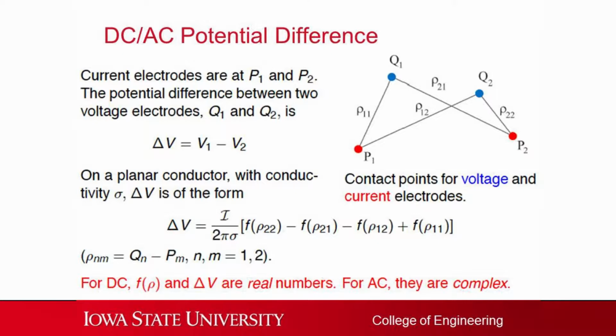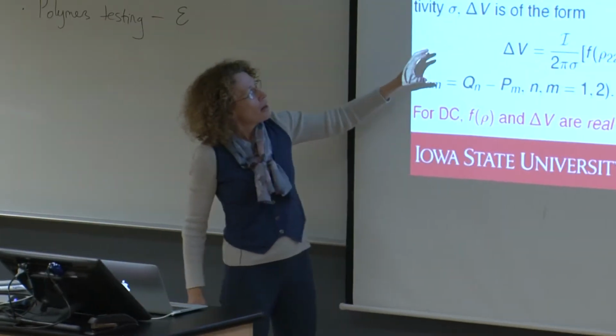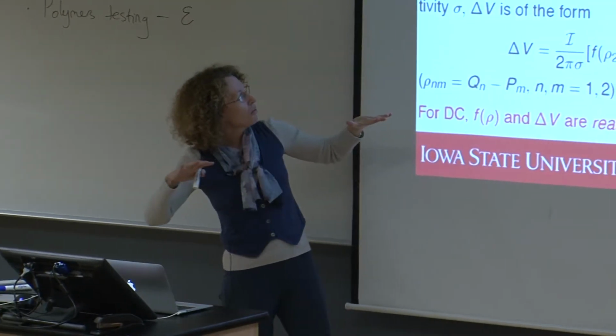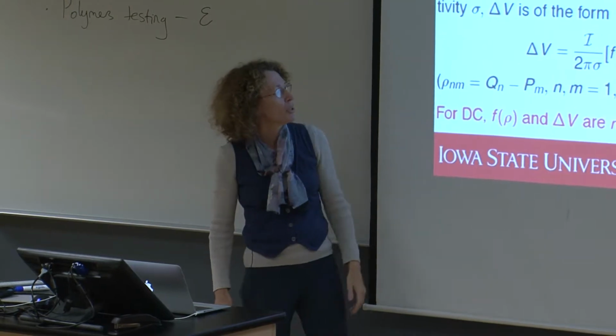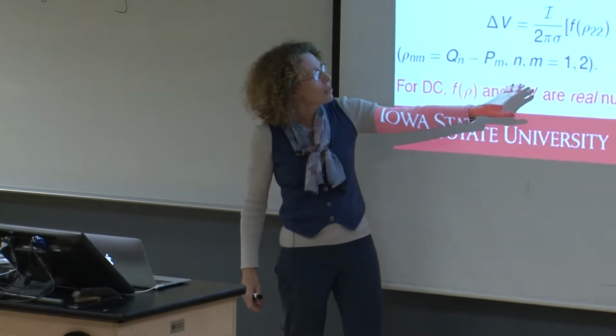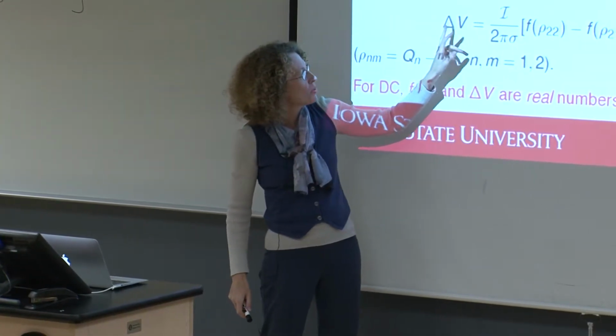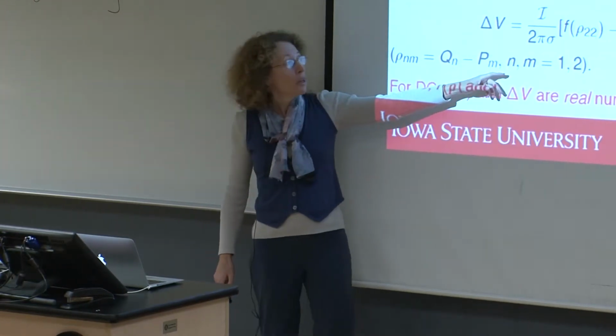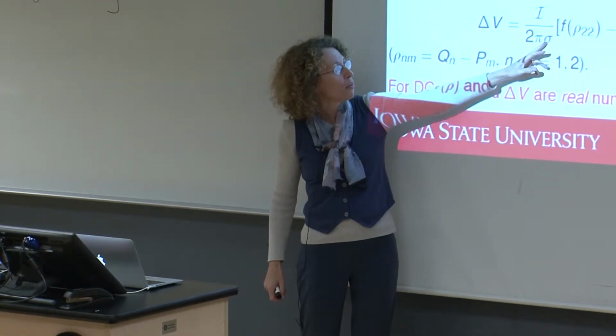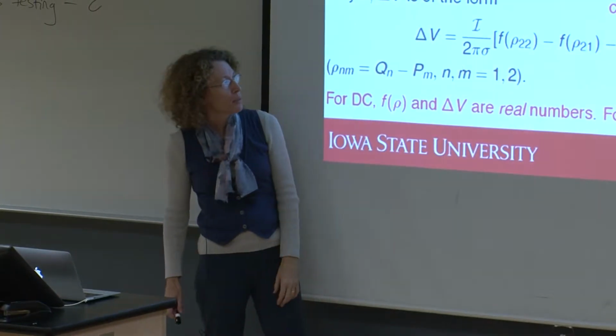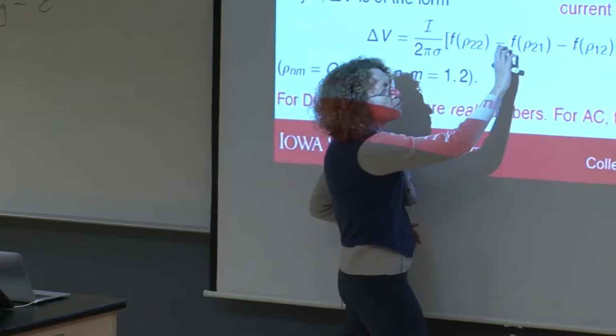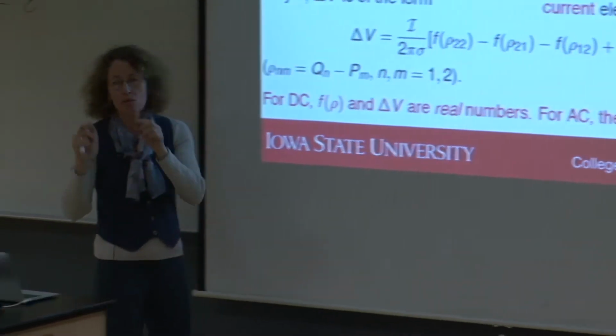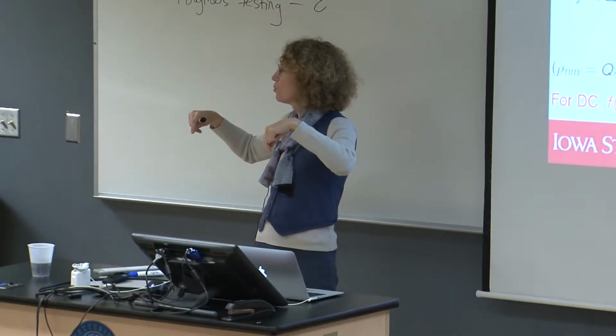So this potential difference is the voltage at position 1 minus that at position 2, which are given by the blue dots there. Now, if you have a planar surface with a conductivity sigma, it turns out you can analyze this system and you find out this relationship. So this potential drop is simply proportional to the current divided by 2 pi times sigma. And you have this function that depends on all those different distances between the points.